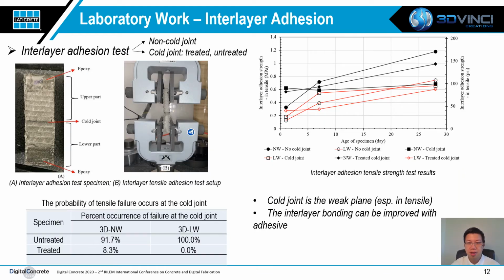To assess the interlayer adhesion between printed layers, we developed a direct tensile test on the printed specimens. Some of the specimens were printed in one run, meaning no cold joint exists. The other specimens were printed with a one-day interval between the lower and upper parts, creating a cold joint between the two parts. For the cold joint specimens, the cold joints were either treated with an adhesive or left as it is.